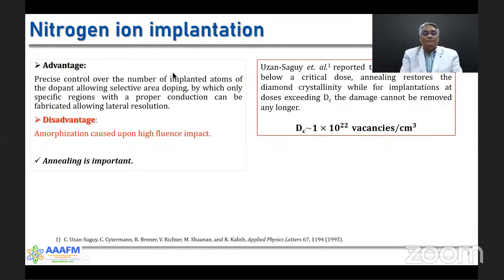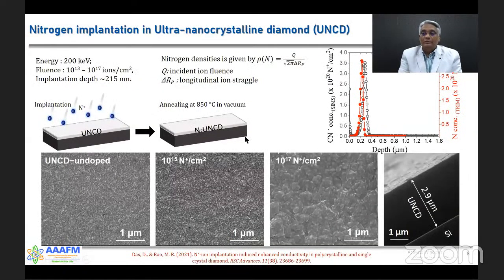So the advantage of nitrogen implantation is precise control over the number of implanted atoms of the dopants. So you can precisely control, then you can tune the conduction inside the lattice. The disadvantage, of course, is amorphization of the lattice due to high ion impact, which can be solved, of course, by the process of annealing. So that's what we have adopted in this study.